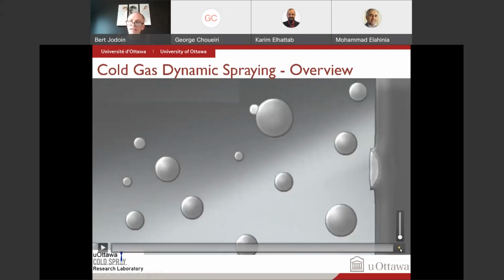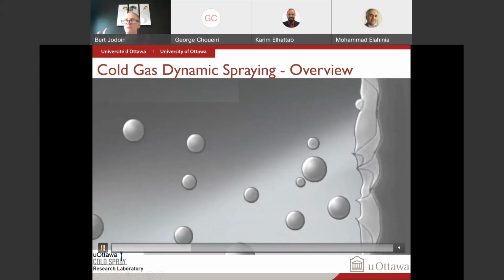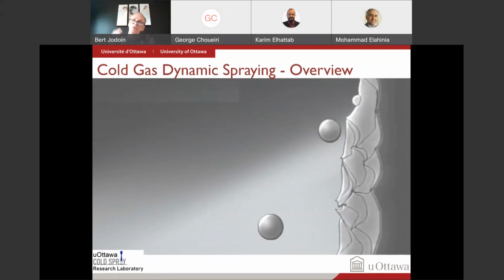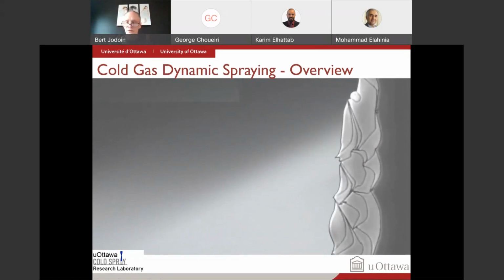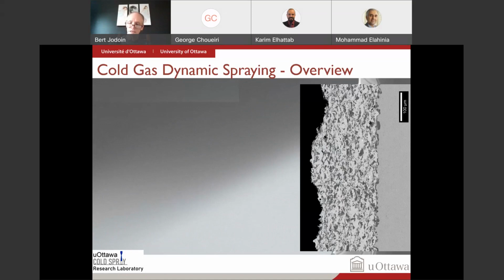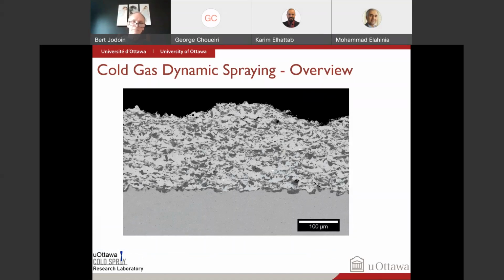And if you're doing this many times, if you have many of those tiny micron-sized particles that you project against a flat surface, they will all deform plastically and stick together and accumulate to form a coating, which might be of various thickness depending on the parameters and for how long you spray. And here I have illustrated a real coating that I'm just turning around. So you have the original flat plate here that you wanted to coat with a special material. And this is your coating here, about 150 micron, 200 micron in this case. And you can see that the coating is made of two different materials here. In this case, it's, I think, alumina and aluminum. So this is the process and how it works.